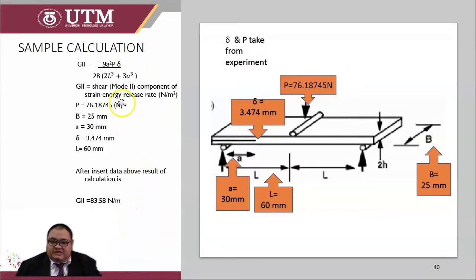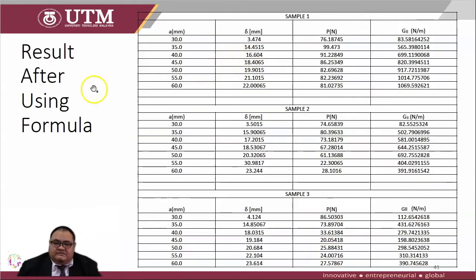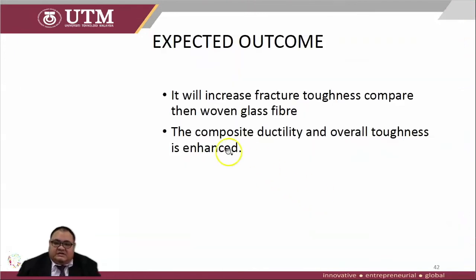This is a sample calculation, where P is 76, B is 25, A is 30, displacement is 3.4, taken from the experiment, and L is 60, the length here. After inserting the data above, the result of the calculation is 83.58 for G2. And this is all the results after using the formula for sample 1, sample 2, and sample 3. The expected outcome is increased fracture toughness compared to woven glass fiber. The composite is more ductile and overall toughness is enhanced.